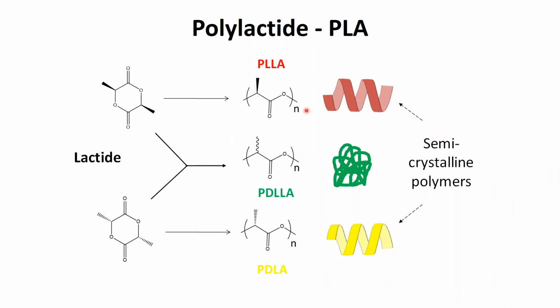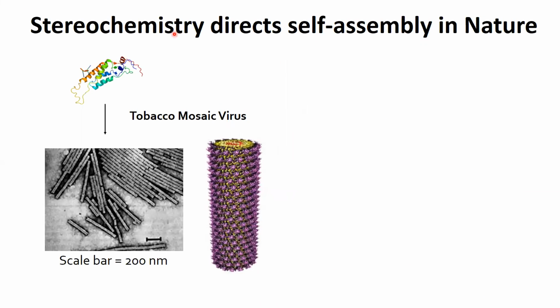So the interesting thing with these two polylactides is actually they're semi-crystalline. And what we've been trying to do with these polymers is use them to create nanoparticles that are of a similar size to some of nature's nanoparticles. The example of that I'm going to show here is this protein that assembles to form a tobacco mosaic virus, which forms this amazing, beautiful rod-like structure. This scale bar here is about 200 nanometers. So these are about 1,000 nanometers in length, and they're perfectly well defined. And the stereochemistry of this building block leads to this beautiful rod-like formation.